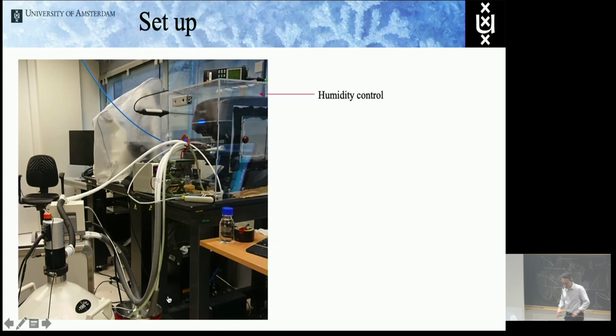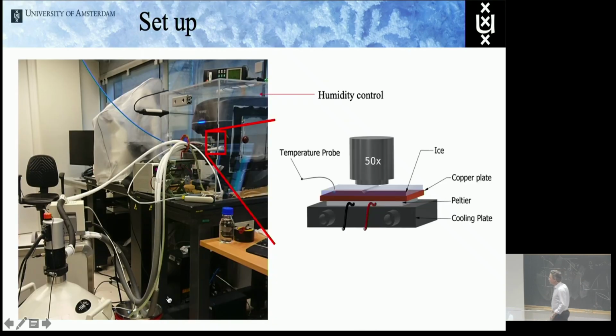But first, the hard work of Menno, because we wanted to do this quantitatively under the profilometer. This is an optical confocal profilometer, and it basically scans through the surface and looks at the changes in reflection, and then transforms that into a depth profile. That's why it's called a profilometer. But you need to do that at controlled humidity, so we put the whole thing in a box, and in the box is a cooling plate, a layer of ice, a very largely magnifying objective, and Menno, who's not in the box. I've tried convincing him to be in the box, but he doesn't want to.